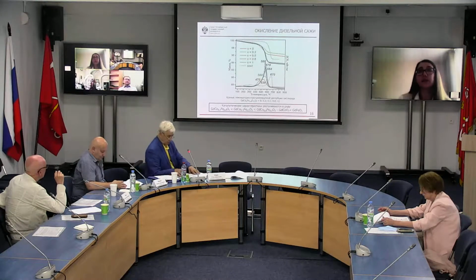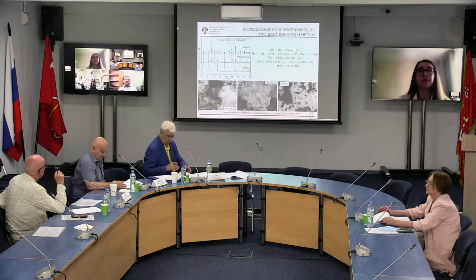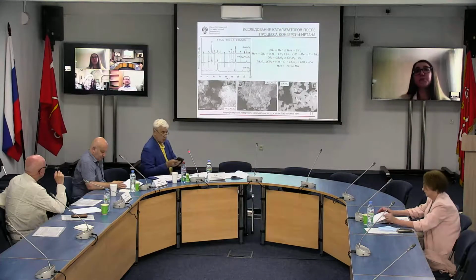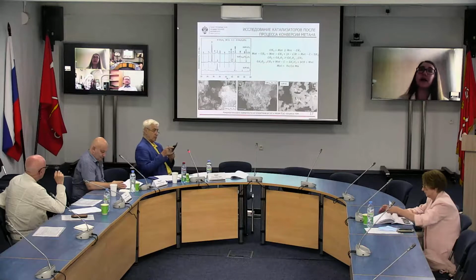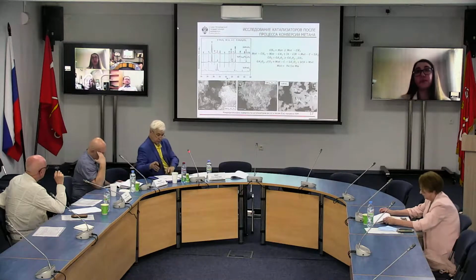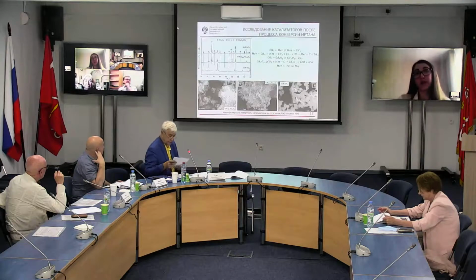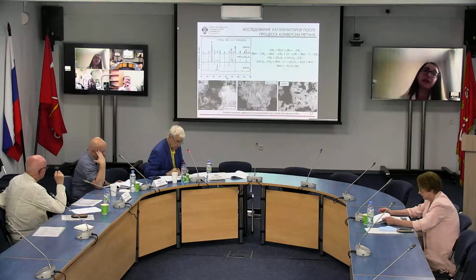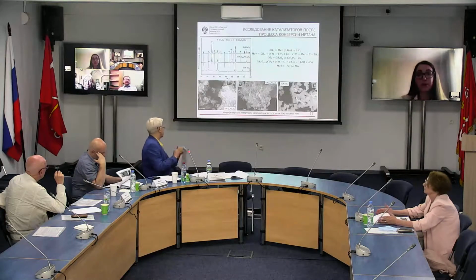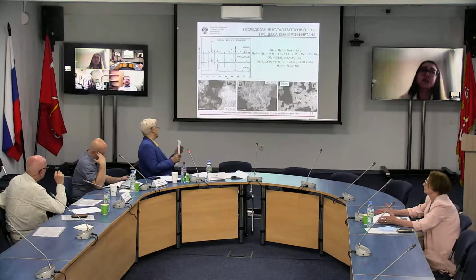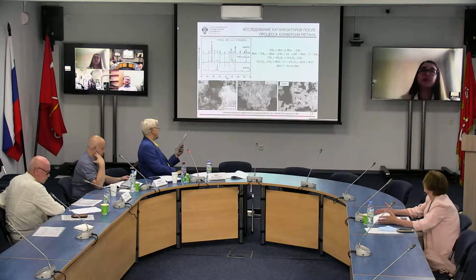And in conclusion, I would like to mention the stability of the developed catalysts. In order to obtain a full understanding of phase changes that happen during this catalytic experiment, we held X-ray phase analysis. And on the slide you see the results of the study of the phase of samples after the study of catalytic characteristics at 950 degrees Celsius during 120 hours.